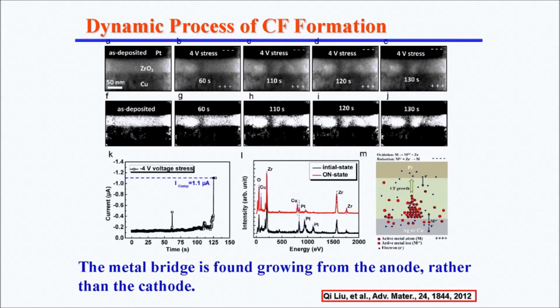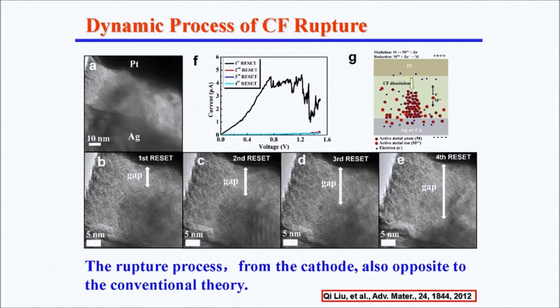More clearly, this is a fresh device. When stressed, we can see the filament formed. Also, we can see the second filament formed. Meanwhile, we can see the curve, the set process taking place here. Also for the rupture process, this is the device after it is finally set. We can clearly see the filament formed here. When we use the rupture, after the first reset process, the filament is already broken, but we don't set it again. That means we further break it. Then after one by one, finally the whole filament can be broken. So this gives the hardware evidence of the filament growing and breaking process.